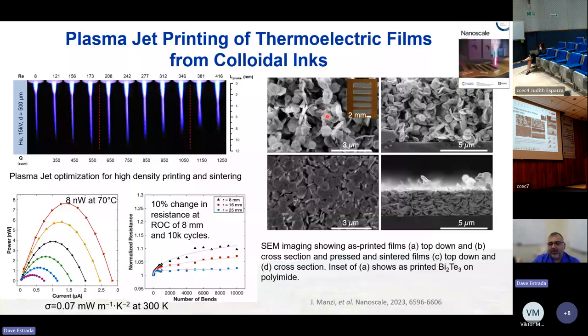So we had to add a cold compaction step where we just squeeze this between two Teflon sheets. And then we were able to get good conductivity and actually get some power harvesting from the thermoelectrics deposited with plasma jet printing. Shown here is just 8 nanowatts as our peak power at a 70 degrees Celsius temperature gradient, which is good enough for some sensing applications. And what we did also see is that after 10,000 bend cycles over a really aggressive radius of curvature of 8 millimeters, we're only getting a 10% change in the resistance.